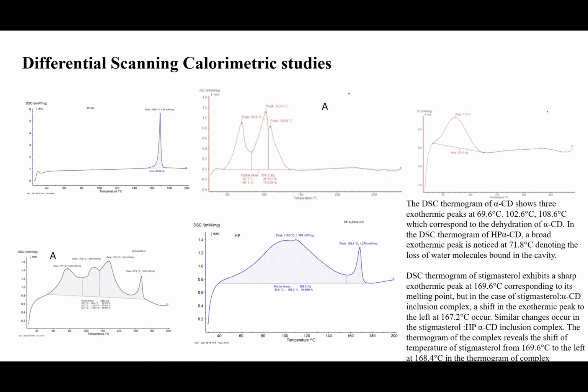So DSC studies I have taken for the solid inclusion complex samples. It is one of the methods to confirm the inclusion complexes. So this is the DSC diagram for stigmasterol, and this is for alpha CD, and this is for HP alpha CD. This is for the inclusion complex of alpha CD with stigmasterol, and this is the DSC thermogram for HP alpha CD with stigmasterol. The peaks here, when the individual compound is there, peaks.